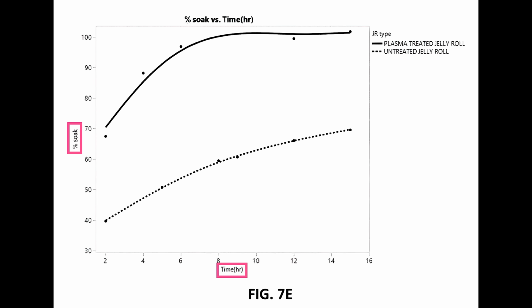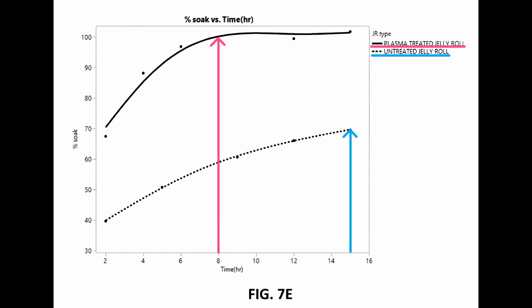Figure 7e shows the percent soak, or how fully wetted the jelly roll is versus time for plasma-treated versus untreated cells that were dipped in a beaker of electrolyte. The plasma-treated jelly rolls took about 8 hours to reach 100% wetting, while the untreated were only at about 70% after 15 hours. An extended test showed those untreated jelly rolls took around 72 hours to achieve 100% wetting, so almost 10 times as long as the plasma-treated jelly rolls.